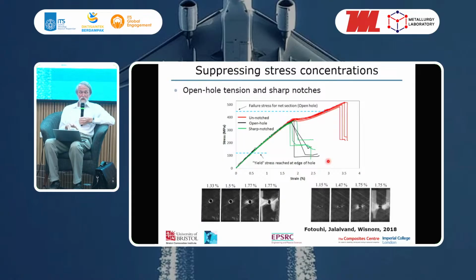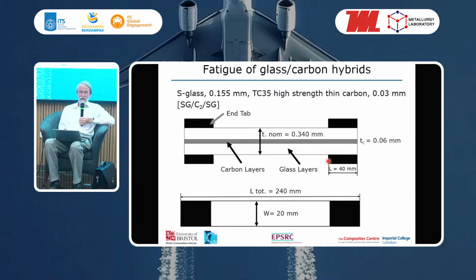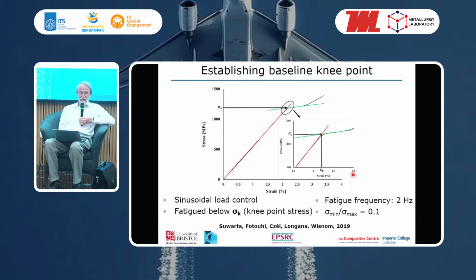So some work that Dr. Putu did on this was to look at the effect in fatigue. All I've been talking about so far was static analysis, but we also did this work on fatigue, where we took a similar material, S-glass composite with TC35, a different fibre, but essentially a very similar standard modulus carbon fibre with thin plies, and 2 of these thin plies between glass, and these specimens were tabbed and then loaded in tension.